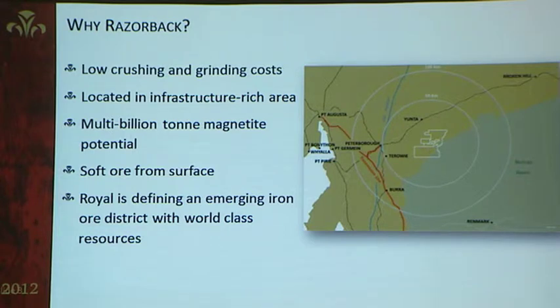Also in terms of extraction at Razorback, given the deposit outcrops and dips shallowly at between 40 and 50 degrees to the north, it will have a near zero initial stripping ratio with low OPEX, and together with existing rail infrastructure and whatnot, CapEx should be low, ensuring that we should be fairly competitive.